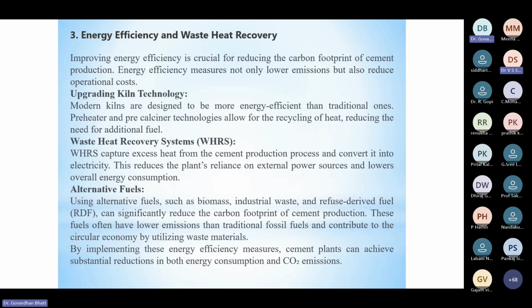Preheater and pre-calciner technologies allow for the recycling of heat, reducing the need for additional fuels. So as I said earlier, the temperature of kiln is 1400 to 1500 degrees centigrade. When it goes to the cooler, the temperature goes down to 150 degrees centigrade. And then this heat can be recycled in preheater, and we use this heat in preheater for the mixing of the cement powders.